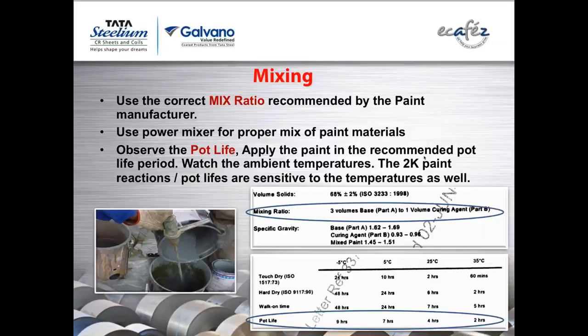But all chemical reactions are temperature sensitive. Usually, as a thumb rule, for an increase in temperature by 10 degrees centigrade, the speed is going to double. So that means those 4 hours at 20 degrees centigrade are going to become 2 hours at 30 degrees centigrade, going to become 1 hour at 40 degrees centigrade. Look at the last table at the bottom right side. At -5 degrees, the pot life is 9 hours. At 5 degrees, pot life is 7 hours. At 25 degrees, pot life is 4 hours. At 35 degrees, pot life is 2 hours.